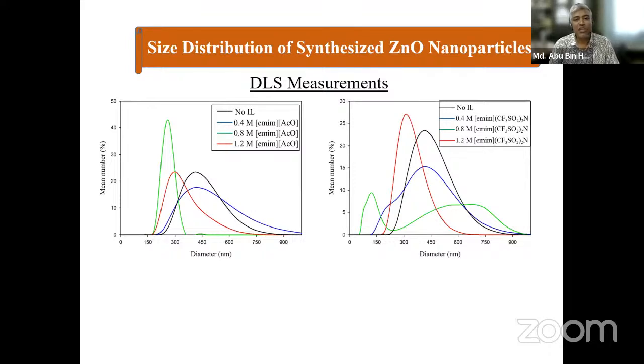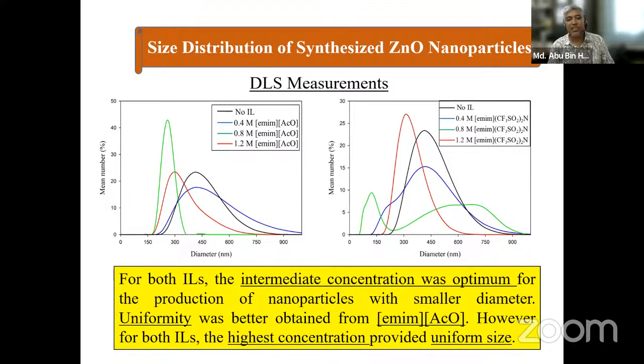Dynamic light scattering measurements were again used for a gross approximation of the variation of the size, and we can see that this is zero ionic liquid. Here we can see this is for ionic liquid. These are single ionic liquids. Like before, we could find a variation here. For both ionic liquids, the intermediate concentration was optimum for the production of nanoparticles with smaller diameter and uniformity. That means if the width is smaller, we can expect a uniform structure. Uniformity was better obtained from imidazolium acetate. However, for both ionic liquids, the highest concentration provided uniform size. So some controllability, some tunability was found for the individual ionic liquids.